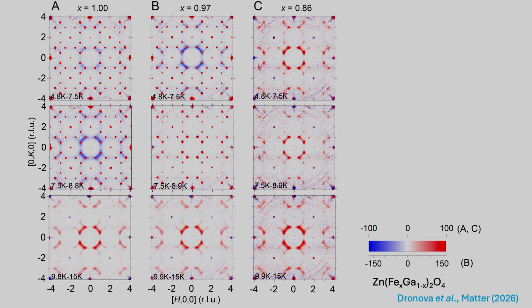So now we look at our data slightly differently. What we do here is we take the difference between two neighboring temperatures and see how the spectral weight evolves from temperature to temperature to temperature. So at the high temperature, from 10 to 15 Kelvin, you can see the red is accumulation. So basically all three systems have a spin spectral weight accumulating everywhere in the reciprocal space. You don't see any blue here. These are accidental fluctuations, of course. But the spin spectral weight is positive across all three samples.